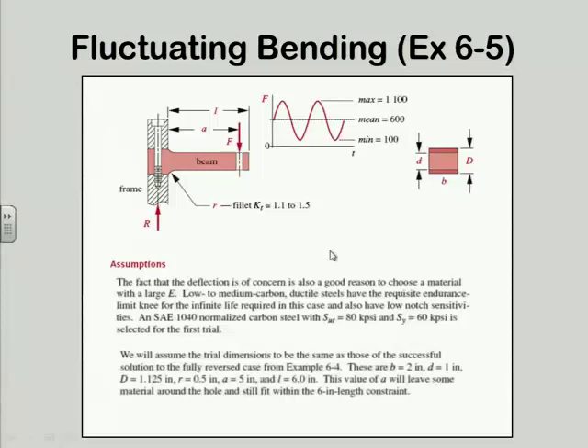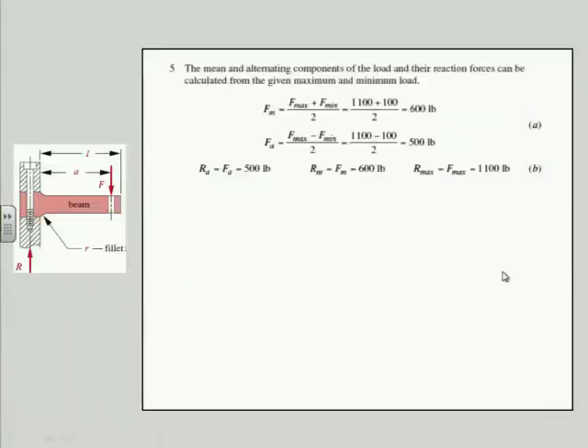So here's the numbers that we ended up with before. 2 inches wide, 1 inch deep. Big D, which is the piece in the wall, is 1 1/8 inch. Half-inch radius in the notch. Distance A is 5 inches and distance L is 6 inches. So that's where we ended up with the fully reversed case before.